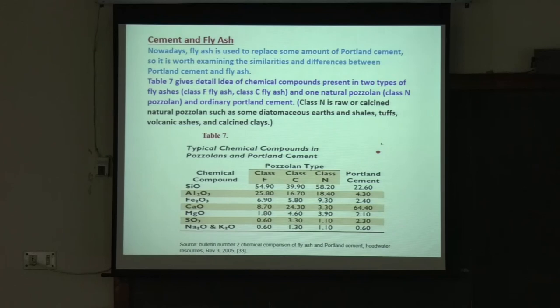So the typical chemical compounds in pozzolans and portland cement: you have silica, silicon oxide, about 55% in class F. In class C, you have about 40%. And in class N, about 58%. And if you look at portland cement on its own, it's only about 23%. So the content of silicon oxide, I think it should be SiO2. Yes, SiO2. Please put the 2 in, it is missing somewhere.